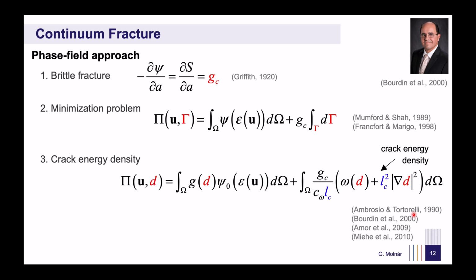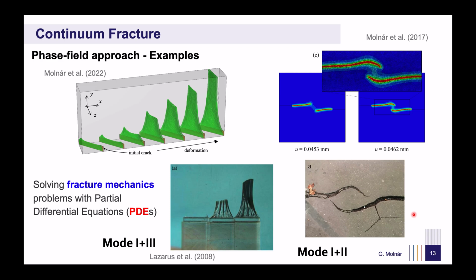The breakthrough came when Bourdin, Francfort and Marigo introduced the crack surface density, utilizing the Ambrosio-Tortorelli functional to diffuse the crack over a small region, thereby transforming the discrete problem into a volumetric one. However, they ensured that when the internal length scale lc tends to 0, the model recovers the original discrete problem. In a sense, the phase field model allows us to solve fracture mechanics problems using variational methods. One of its major advantages is that it does not require any additional criteria to model mixed mode crack propagation and reproduces experimental observations robustly.